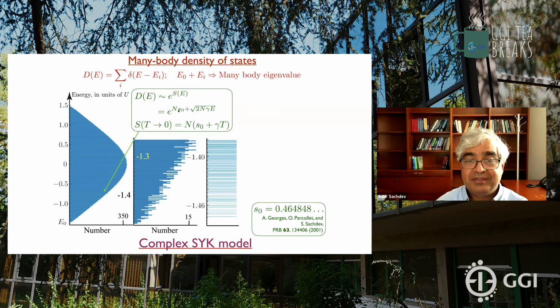there's an entropy as the temperature goes to 0. So there's a correction here, which tells us that even as the energy goes to the ground state, there's an exponentially large term. This was not present. S0 was 0 for the free electron problem. Now, that might seem like you're violating the third law of thermodynamics. How can there be an exponentially large ground state set of levels? But the point is, this is not a ground state degeneracy. It's a 0 temperature entropy.